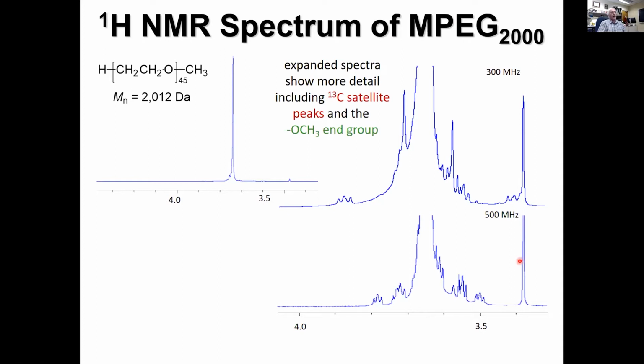But if you go to 500, you see the methoxy, the PEG, and you see this peak here and this peak here. Those are the two things that had that magenta dot on the thing before. If I wanted, I could have also had an internal standard like dichlorobenzene here as well.